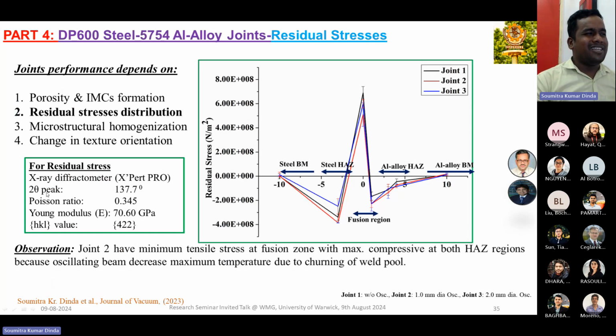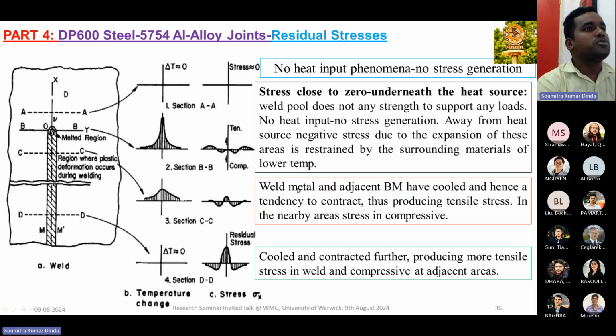Suppose that we took the 2 theta peak at the highest strong peak, that is 137.7 degrees, and we did the X'Pert HighScore analysis, and then found that joint 2 shows the tensile property is the minimum, the red one, but the compressive stress is maximum. So this is more favorable in the case of joint 2. So why does this type of curve form in welding for the residual stress distribution? We can discuss that with the help of this diagram.